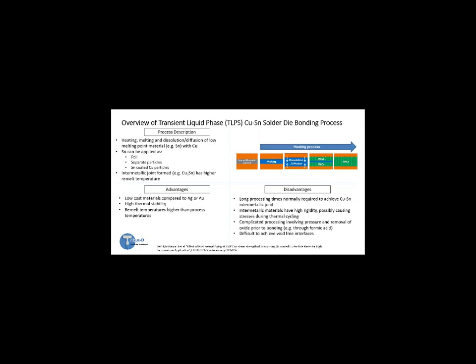And so finally, in this quick review, the transient liquid phase route of using a low melting point material in between high melting point material, and then relying on melting into diffusion, has had a lot of action research-wise, and has the potential to get towards higher temperature operation using lower temperature materials, and also using common materials such as copper and tin to achieve it. But realistically, it relies on growth of intermetallic materials. There's complicated processing because you've really got to have clean surfaces to get the effect, and it's difficult to achieve void-free interfaces when you're going through.